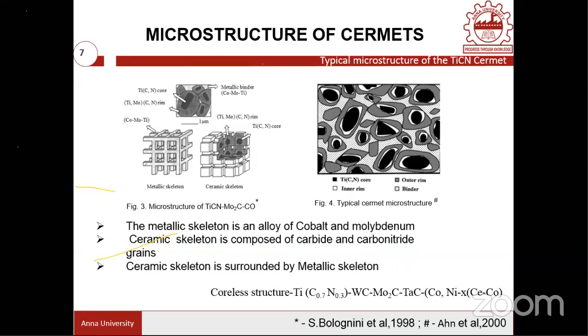As a result, there won't be any core, but instead you will have an inner rim as well as an outer rim, which will be forming. As a result, the problem with the coreless structure is you will have extremely good toughness value, but the hardness value would be poor compared to the conventional TiCN based material. So here,